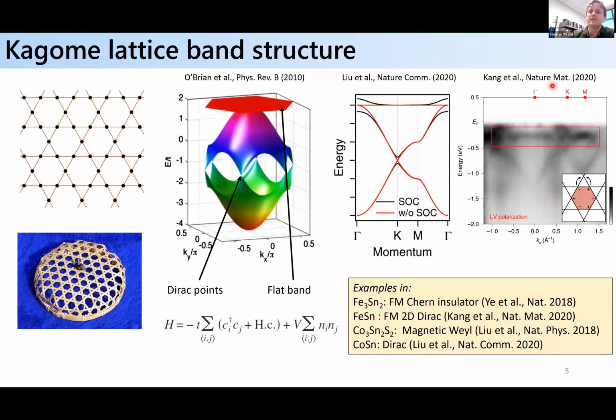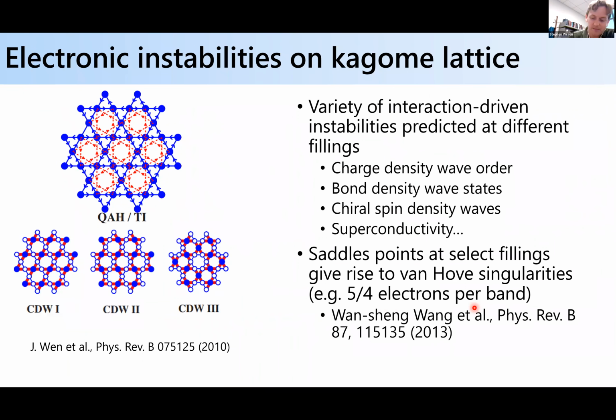And there's been a lot of work in this field in recent years, where systems like iron 3 tin 2 or iron tin, or for instance, cobalt 3 tin 2 sulfide or cobalt tin, have started to realize some effects of this interplay between non-trivial electronic states, but also magnetic order associated with the flat band physics of the system. And here I've just summarized a few examples. And then more broadly, if you just look at tight binding models of a kagome lattice, and look at the various effects that you can realize at different fillings, there's a long history of predicting different types of electronic instabilities on the kagome lattice.